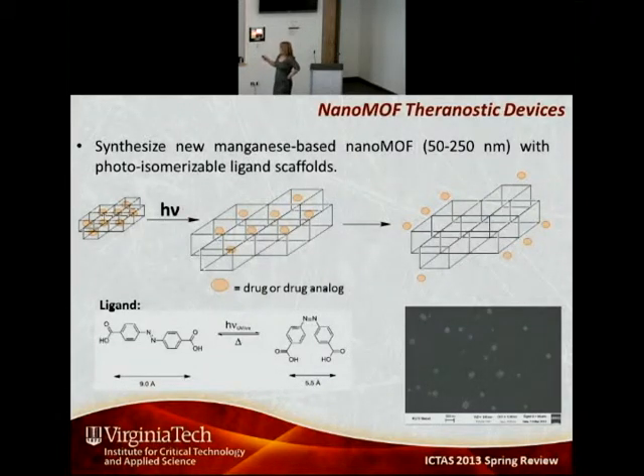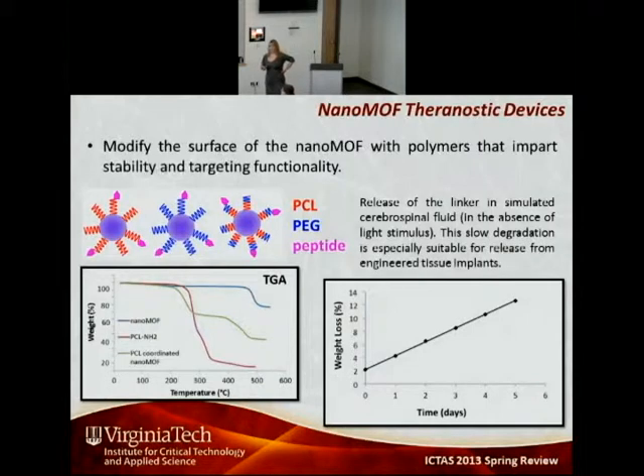And so now this allows us, through this amine functionality on a polymer, to coordinate to the free surface available, metal sites of the nanoparticle, and then the amines on this outside end of the particle will now be available for coupling to affect signaling peptides or antibodies or to targeting functionality.